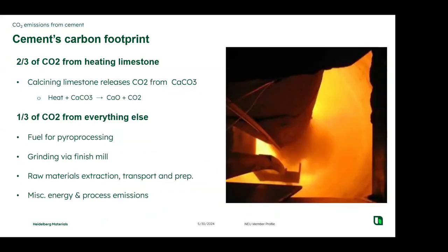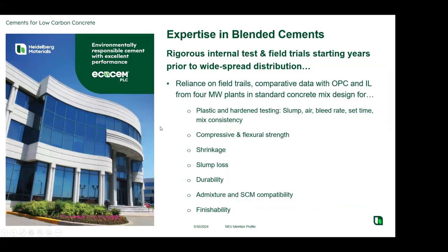I talked a little bit about our carbon footprint for cement. It's important that people understand that 2/3 of our CO2 emissions or our carbon emissions associated with manufacturing clinker come from heating up the limestone. It's a natural process. When you apply heat to calcium carbonate, which is another name for limestone, you generate calcium oxides and CO2. The calcium oxides are bound up with silica compounds in most cases, and that's essentially what we're capturing to make our clinker. And the CO2 is a byproduct from that process. 2/3 of our emissions come from these process emissions, and that is something that we really can't change. Our 1/3 is where the efficiencies come in. This is where alternative fuels, grinding efficiency, burning efficiencies, and utilizing the right raw materials, et cetera, all help us reduce that piece of our emissions.